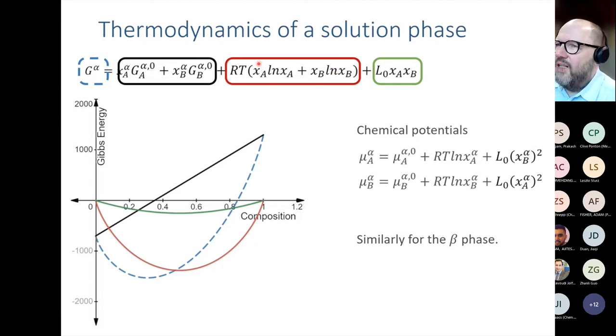Then we've got the ideal entropy of mixing, so the configuration entropy. So there's no interaction in there. It's just the different ways we could arrange the atoms on the crystal lattice. So there isn't even a free parameter in there. That's described by the red line below. And then we have an excess term. And that excess term can describe whether we would find that an alloy shows interactions between the chemical elements that are either attractive or repulsive. And I like to restrict myself to attractive interactions because it's easier for the time being.